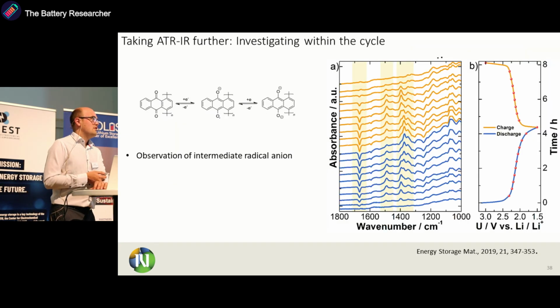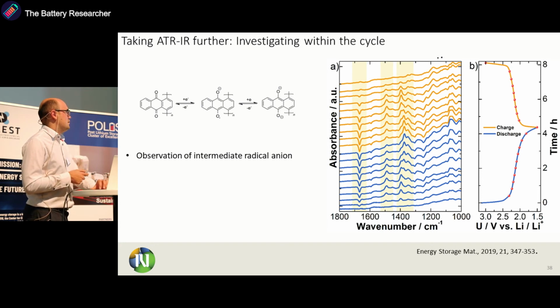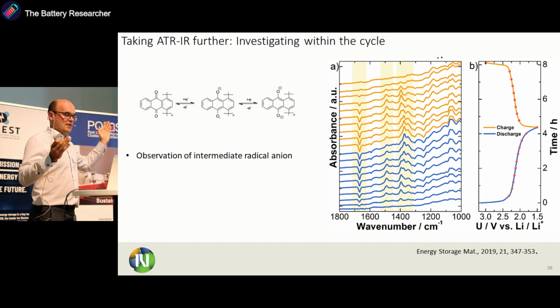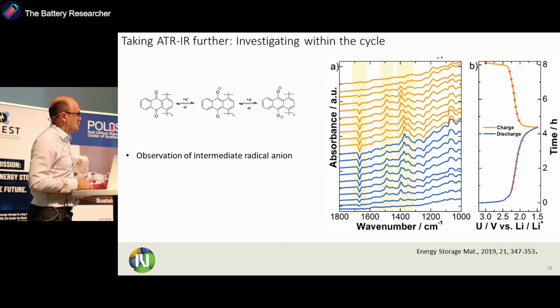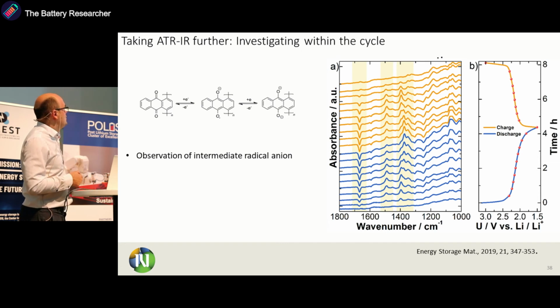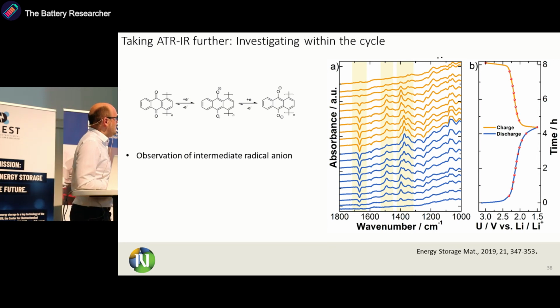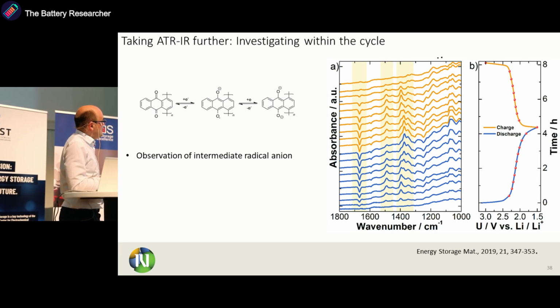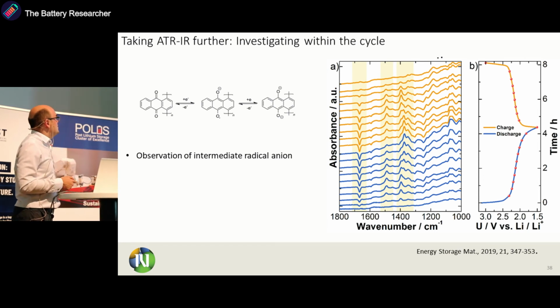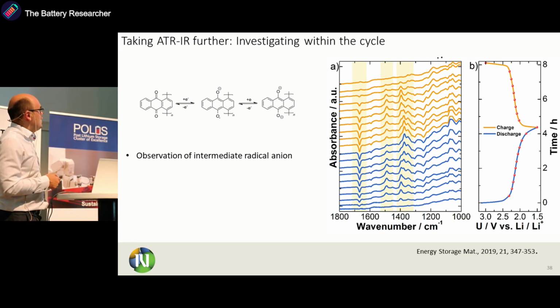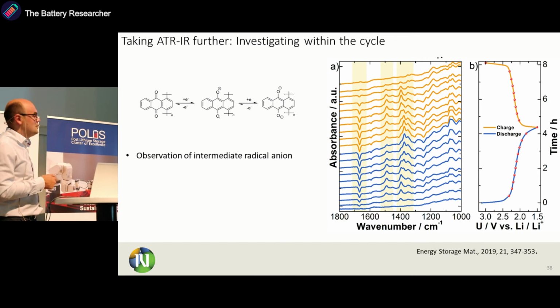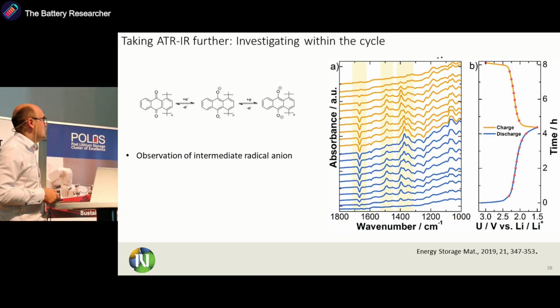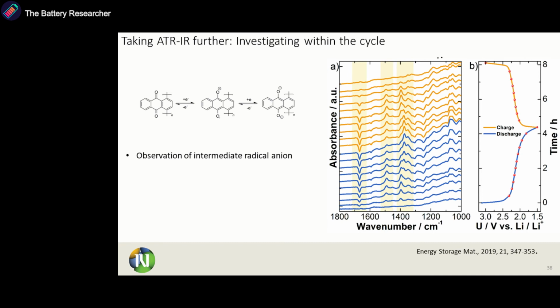We can take this method even further, so not just taking start of the cycle and end of the cycles, but also subtracting cycle in between. And when we did this in this polyanthraquinone compound, it was quite interesting that we were able to identify some peaks which are reappearing in the middle of the cycle and then disappearing towards the end and then appearing in the middle here again. And this is actually what showed us, basically, this does not go directly with 2 electron exchange here, but there is an intermediate radical anion in between here. And these peaks here, they belong to this radical anion.